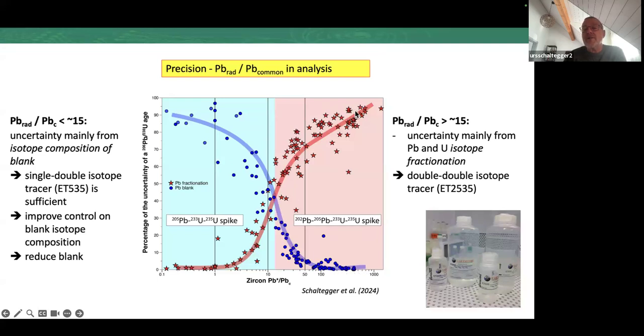And above this value, this source of error gets less and less important, but the error is dominated by the fractionation, so the isotope fractionation which happens in the mass spec. And for such analyses, at high radiogenic to common ratios, we use the double tracer solution, 202 lead, 205 lead, 233 uranium, 235 uranium, so the double spike can be perfectly used to correct online for the fractionation.